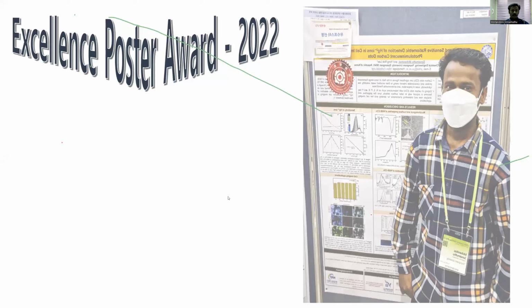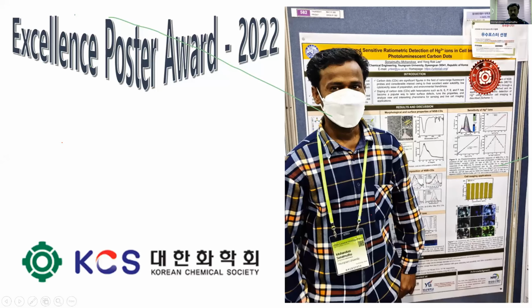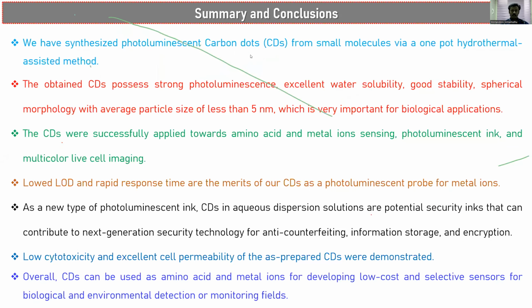So finally, the summary and conclusion. We synthesized the photoluminescent carbon dot from small molecules through a single pot hydrothermal assisted method only, without any solvent, without any precursor. We can get carbon dots that possess strong photoluminescence, excellent water solubility, and good stability. We can get a morphology with average particle size less than 5 nanometer.